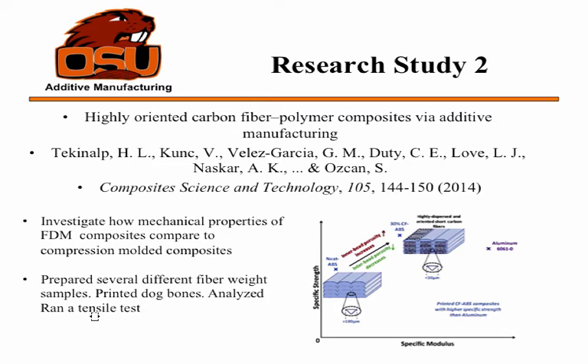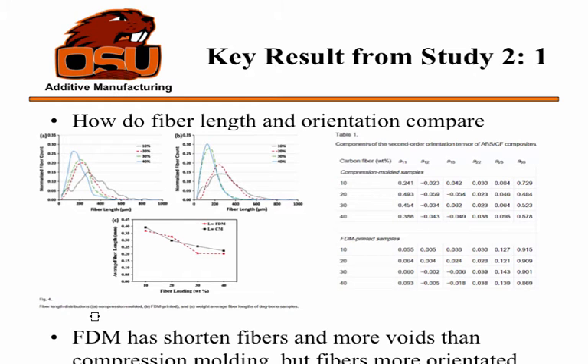The second study was highly oriented carbon fiber polymer composites via additive manufacturing. How this is applicable to the process we're looking at is that all the fibers in there are highly aligned. They can only come out in one direction on the print head. What these guys wanted to look at, it was a whole bunch of people that did it, was how aligning these fibers inside of the FDM composites compared to a traditional compression molded composite. So what they did was make the polymer filaments up with a bunch of different weights of fibers in there. They printed dog bone samples for tensile tests, then they ran the tests on them. The first part was comparing the fiber length and orientation from the compression molded composites to the FDM ones.